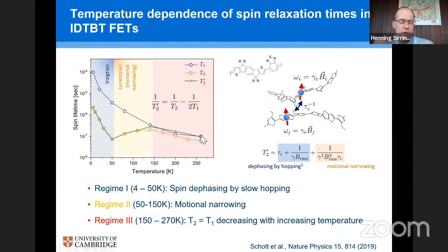So at room temperature, the spin relaxation time is on the order of 100 nanoseconds. And then T2 has a more complicated temperature dependence, where you initially see this regime where T2 decreases with increasing temperature. So that's a regime where essentially the charges are hopping from site to site slowly, and so they have enough time for the spin to dephase.